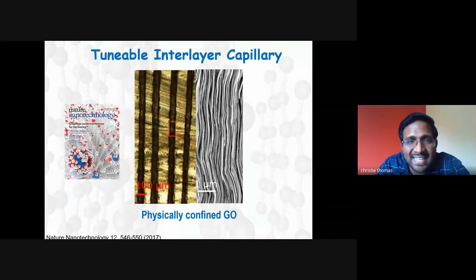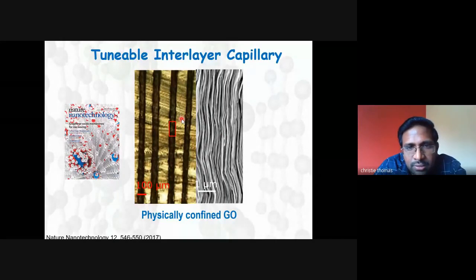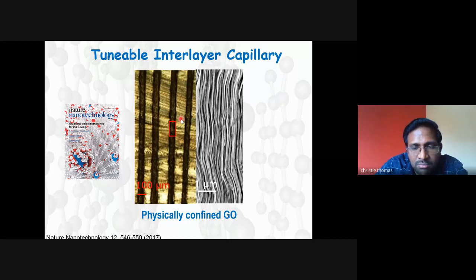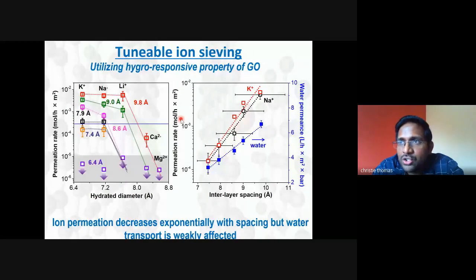So what we tried is we physically confined GO. What you see here is a graphene oxide membrane in the black portion. The SEM picture of that black portion is here. You can see it's like stacked graphene sheets. The yellow portion is an epoxy, like a powerful glue, and that can physically confine GO from expanding or swelling when it is put inside water. So basically we made a tunable interlayer capillary using a physical confinement approach, physically confining the GO using epoxy.